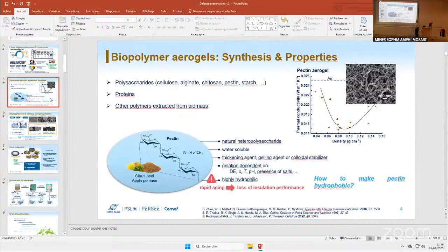Okay, yeah, understood. And then somewhere in that chapter about the compression, you question the very low thermal conductivity values at relatively high density. I think you're right, this raises some concerns, and further investigation is needed to confirm this. With silica aerogels, we have seen the same. We hypothesized that this is due to the nature of the contact. These were hydrophobized silica aerogels, and the new solid state contacts that occur on compression are not chemically grown, and maybe they're more like a point contact. Could something like that also happen?